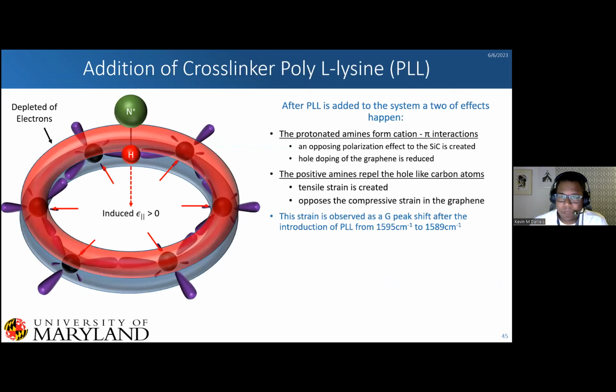And so whenever we put this additional crosslinker, this poly-L-lysine, on top, we have two effects happening. We have these protonated amines forming cation-pi interactions. So this is an opposing polarization field to the silicon carbide, and the doping of the graphene is reduced as a result. And then we have these positive amine groups repelling the holes, like carbon atoms. So we have a tensile strain that's created, and this opposes the compressive strain in the graphene. So we have this huge shift in our material from 1595 to 1589.